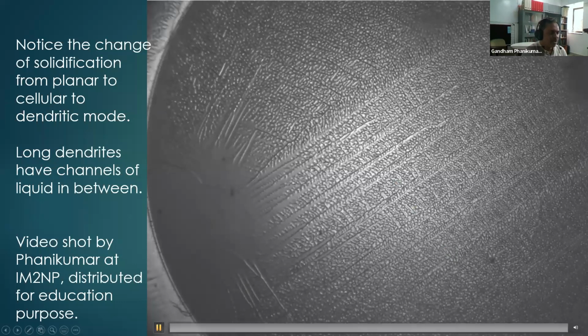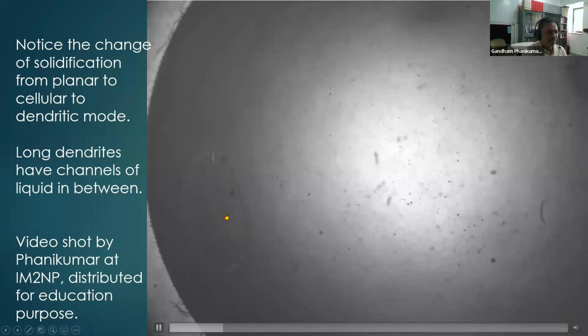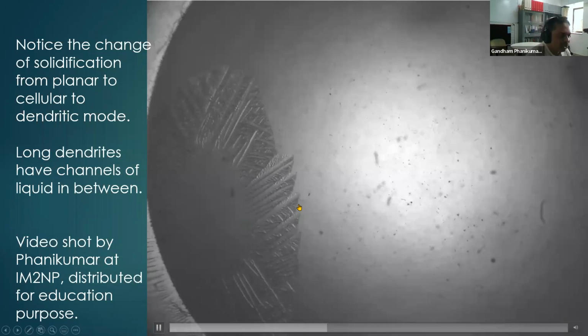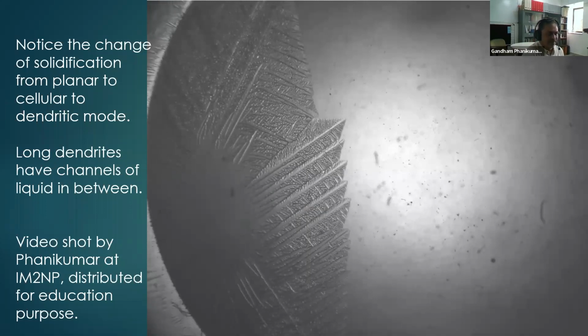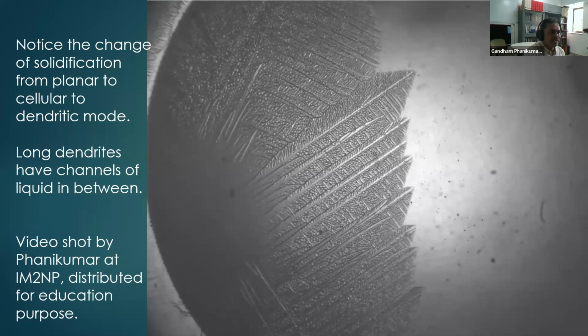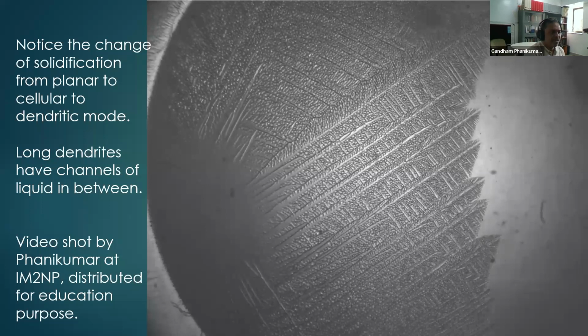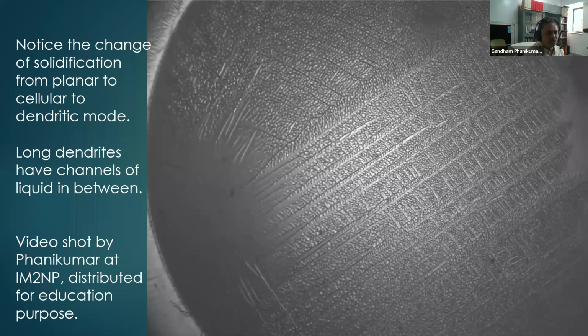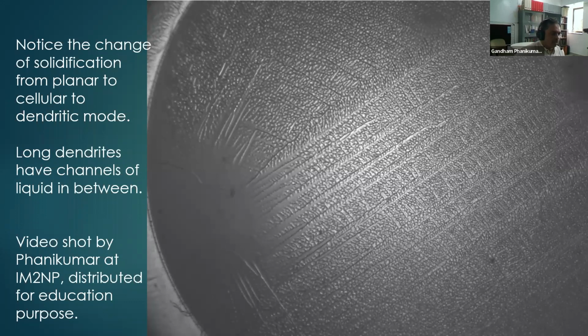Now, the reason why the planar front initially became cellular and then dendritic is because of the instability I mentioned to you, which is caused by the segregation of elements. It's called the Mullins-Sekerka instability criterion. Of course, the starting point of it is so-called solutal segregation or constitutional supercooling. But Mullins-Sekerka instability is a better way of calling it, because in laser additive manufacturing the extreme speeds will play a role, and therefore Mullins-Sekerka is a better way of referring to that.